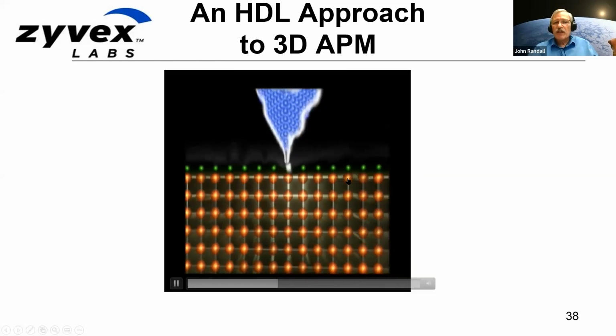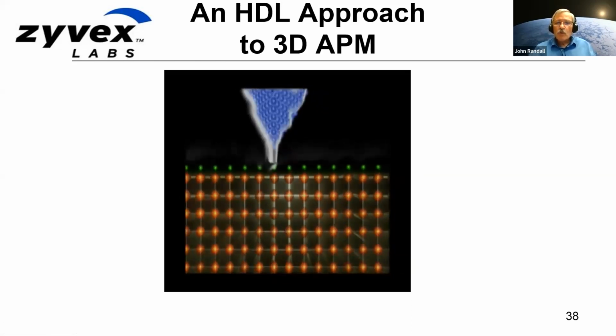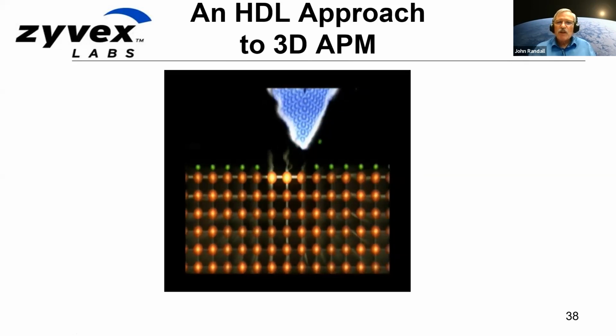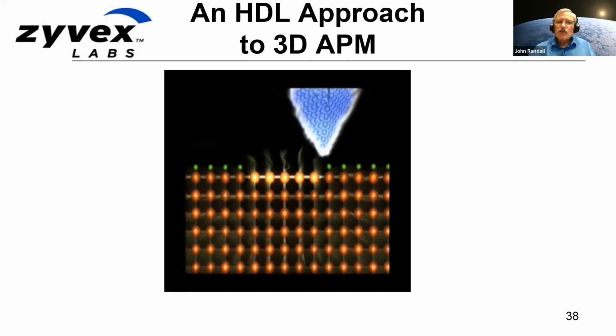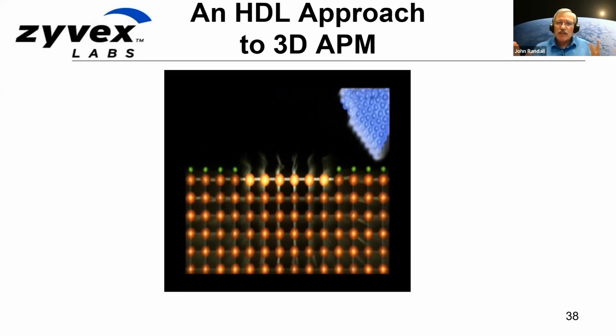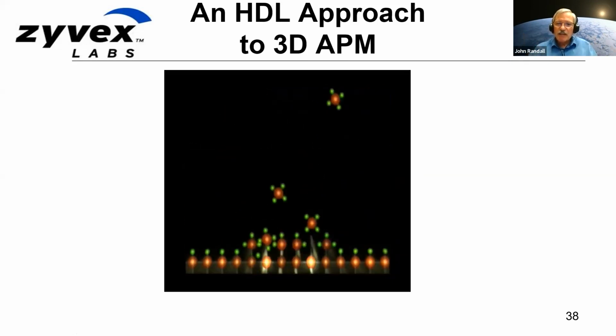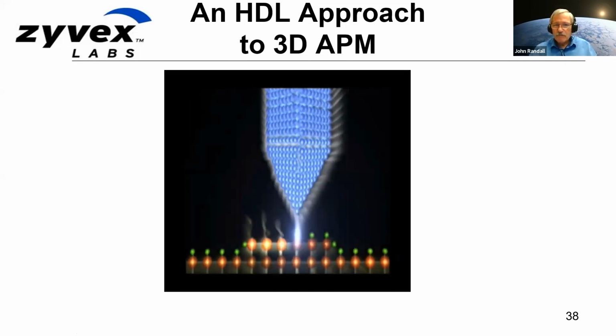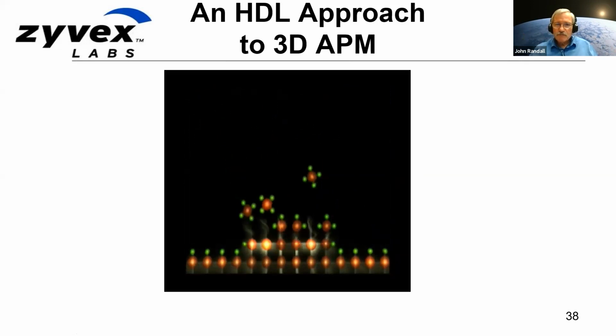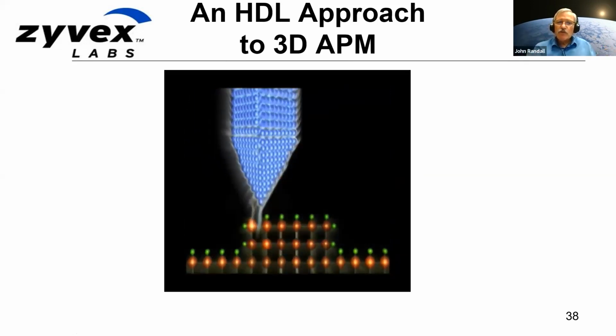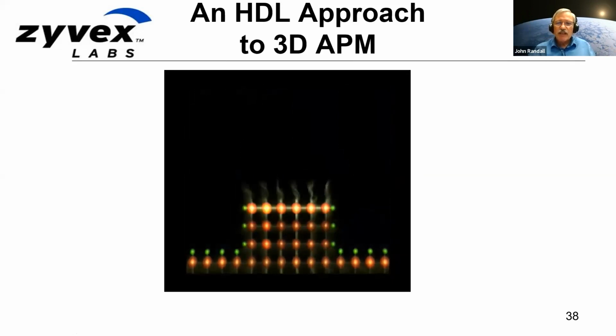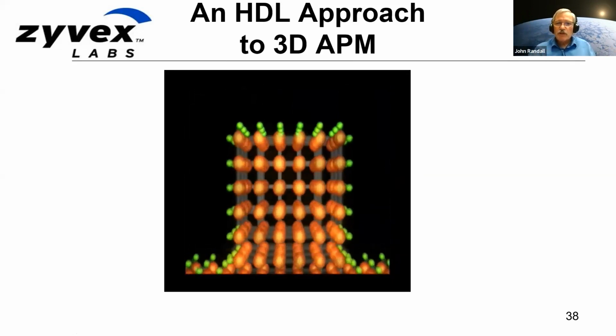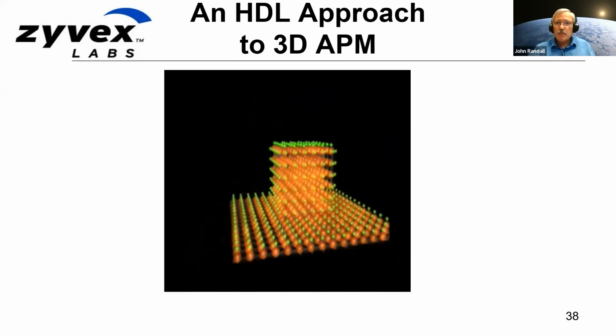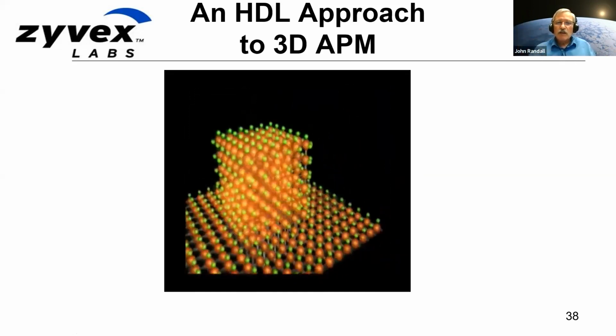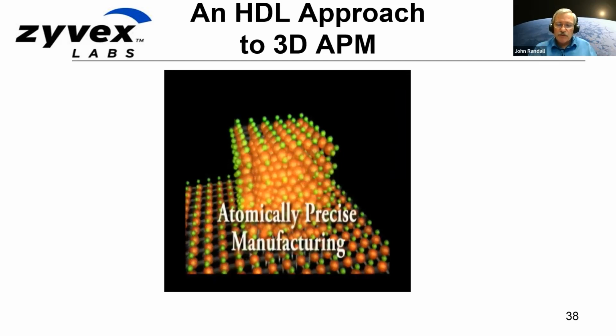We can look at those without disturbing the hydrogen atoms, or we can go in, raise the voltage and current, pop off those hydrogen atoms, then dose with a precursor, and this is what we don't have yet, which gives us a full monolayer of atoms that self-limits. Do lithography again, dose again, and repeat, and do that in 2 dimensions on the scanning, and then we can build up to 3-dimensional structures. We've already demonstrated we can do the silicon epitaxy, but we haven't done it with atomic precision quite yet.